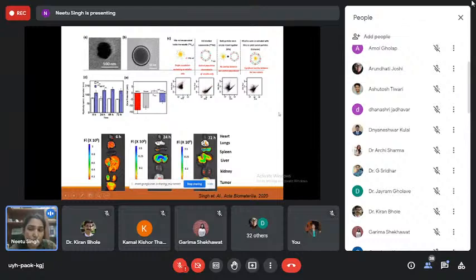So what happens to the, where is it found? As you can see that the tumor, the last one, had the maximum presence after 72 hours. So it was in circulation and slowly it ended up into this. So at the end of 72 hours, you can see how it is growing in the spleen. So 6 hours, nothing is there in the spleen. Over time, it increases in the spleen, clearly suggesting spleen and the liver.